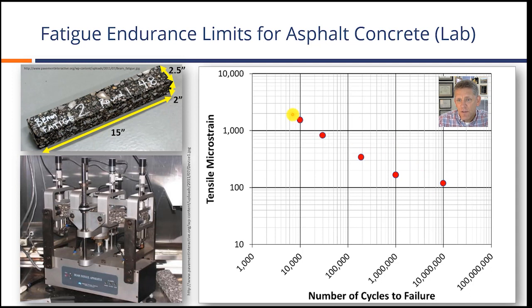And if you run this type of test at a low enough strain level, what you find is that it doesn't continue down. It actually starts to reach an asymptote here. It starts to level off. And for most asphalt concrete materials, that number, as a minimum value, is around 100 microstrain. So for most modern asphalt concrete materials, 100 microstrain is a pretty safe bet.